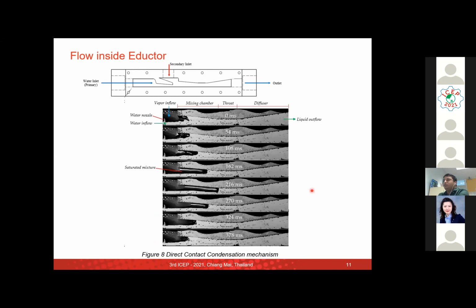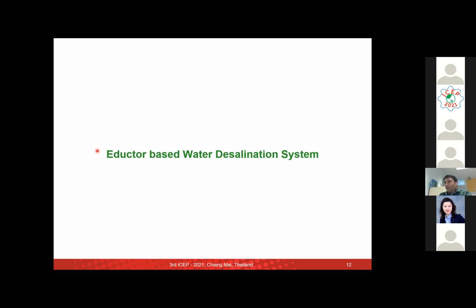This was another study that was performed for flow visualization to see the mechanism of this mass transfer. And we could see that over a period of time, this region of complete condensation oscillates between this suction chamber region and the throat of this eductor. We could see that this oscillation phenomenon was repetitive when the experiment was done.